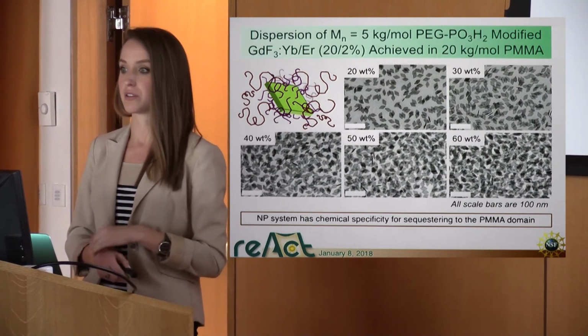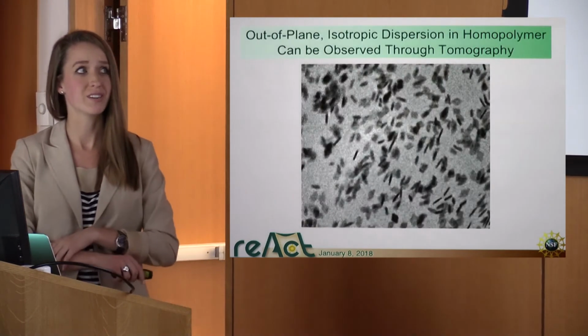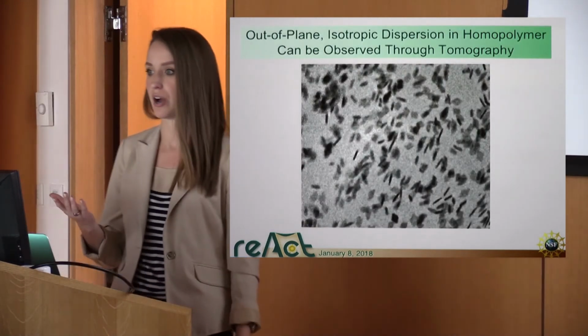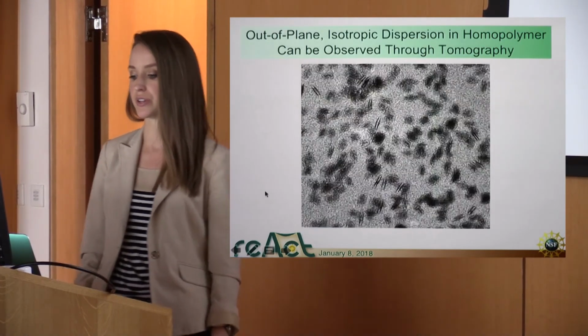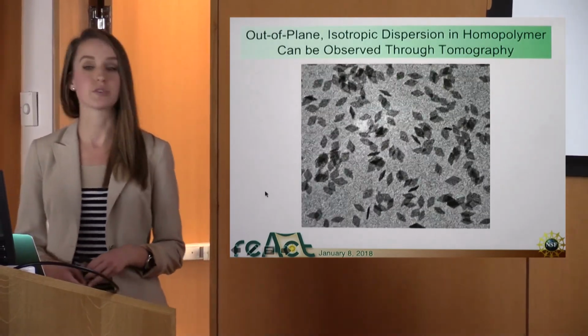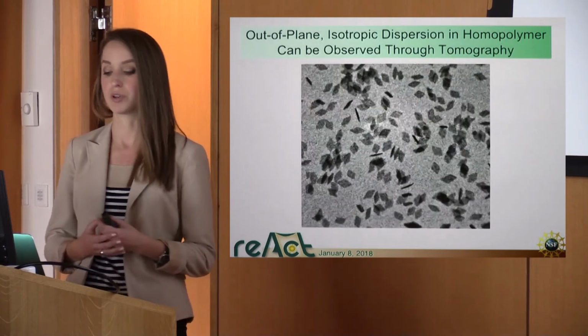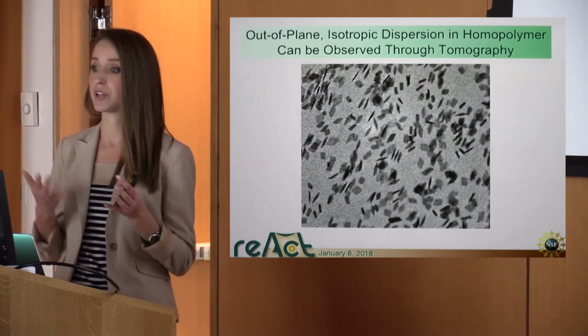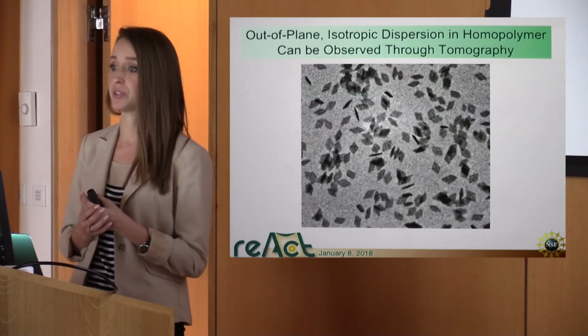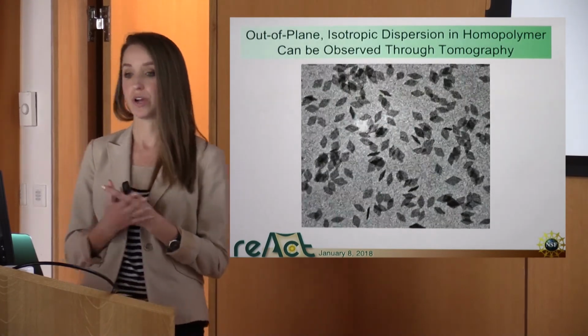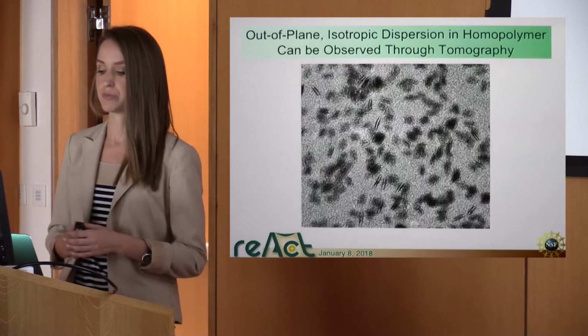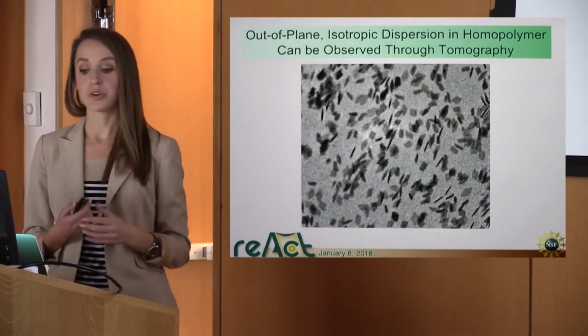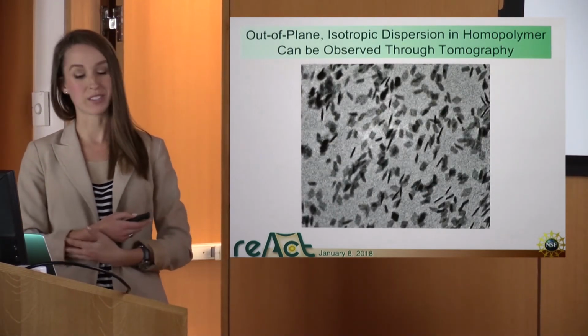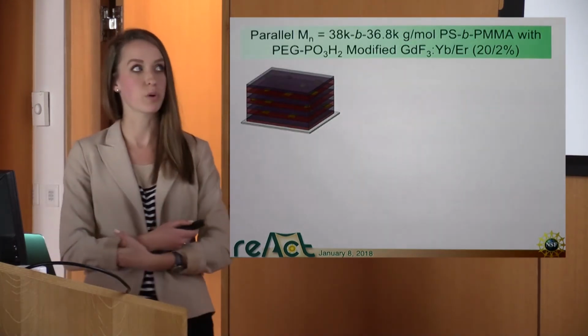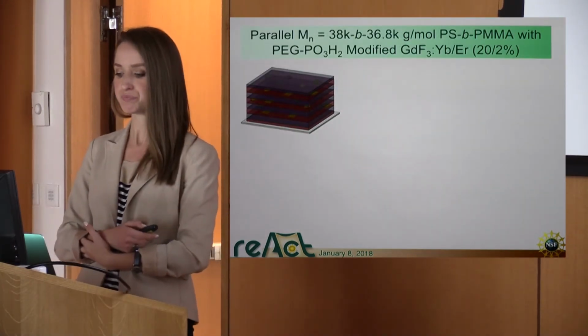So in order to investigate this a little further, I'm working a lot with tomography, where we can look at the out-of-plane dispersion of these particles as well. This is taking a tilt series on the TEM of these particles dispersed in homopolymer. And what we see is that they are randomly oriented within the film, that there is no directed alignment in these films. So in order to establish directed alignment of these particles, I've incorporated them into my block copolymer.